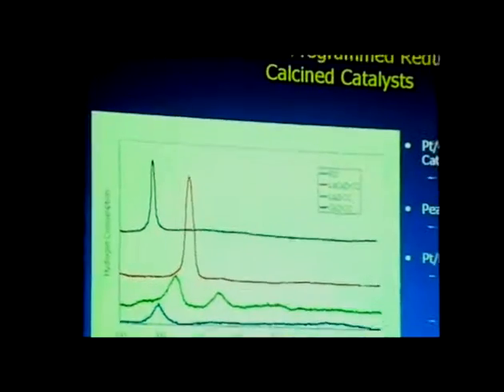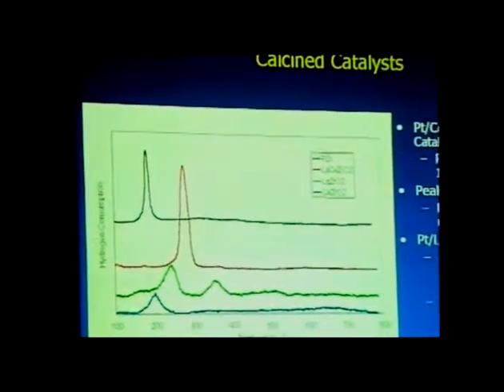And so now what we're seeing is that we have a reduction occurring for the platinum and the lanthana, and possibly either electronic modification of the platinum or changes in the lanthana due to the presence of the ceria.